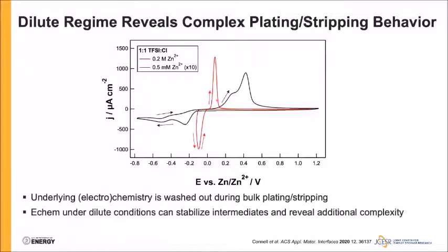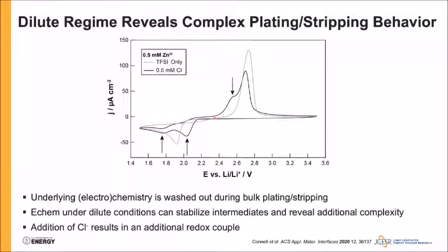When you go to a more dilute system, you actually access mass transport limited conditions. And the reason you now start seeing peaks is because of that mass transport limitation. What this shows is that sitting underneath these individual peaks in the bulk plating and stripping is additional complexity. Specifically, if we compare the response of this mixed TFSI chloride electrolyte to a TFSI only electrolyte, there's an additional redox couple that's present upon the addition of chloride relative to the TFSI only electrolyte.